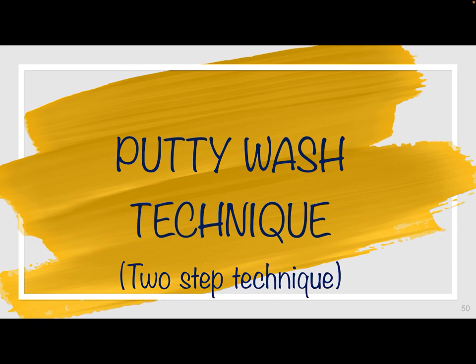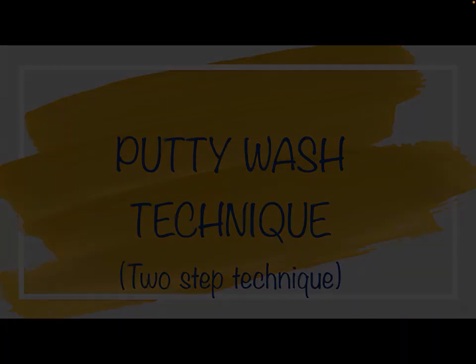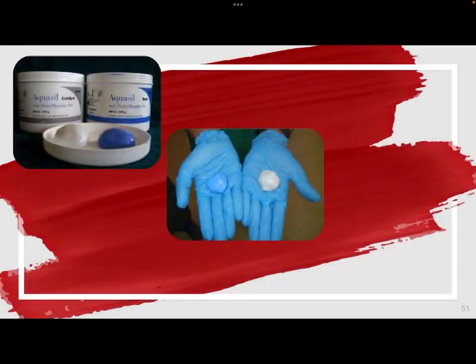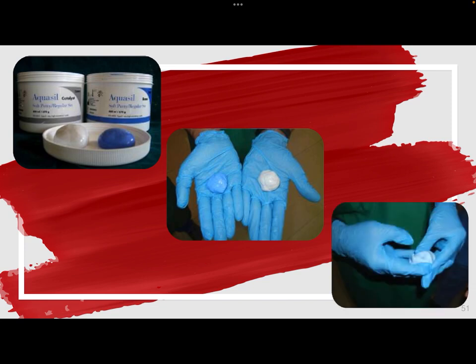Now the other technique is the putty wash technique. It is a two-step technique. In this technique, equal amounts of the putty material, the base and the catalyst, are taken. Also to be understood is that instead of latex gloves, vinyl gloves are used, since the sulfur content in the latex can contaminate and inhibit the setting reaction.